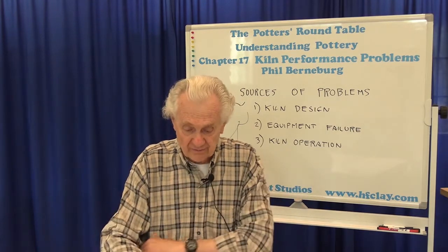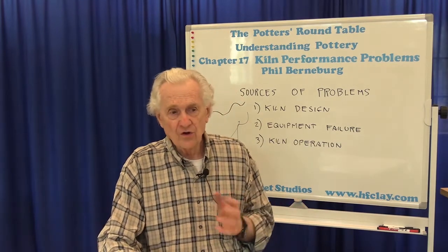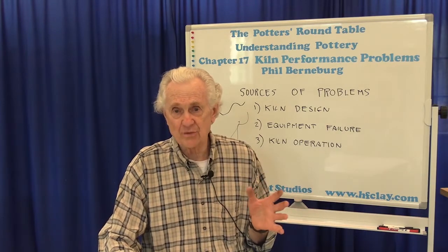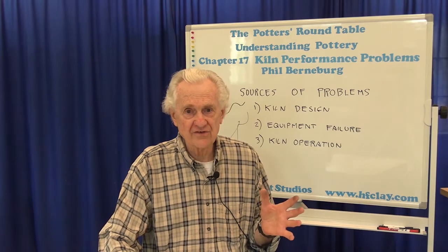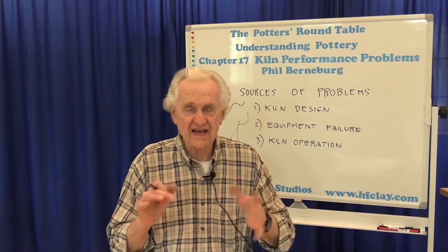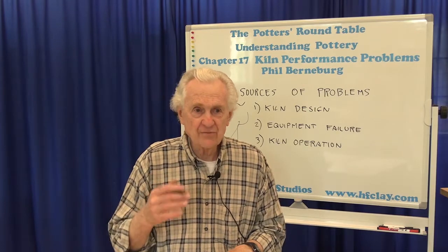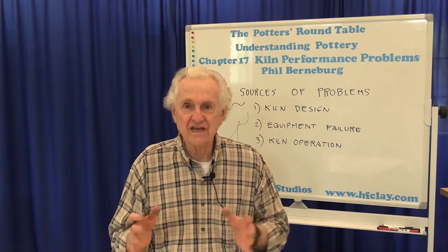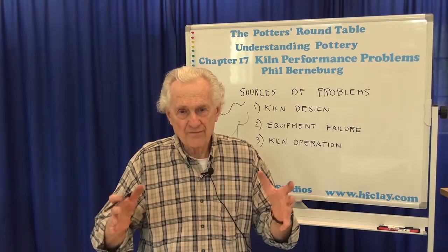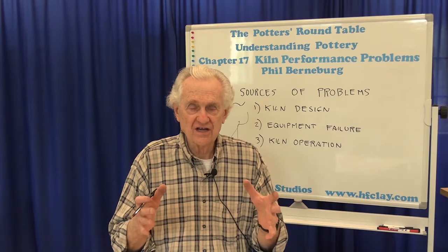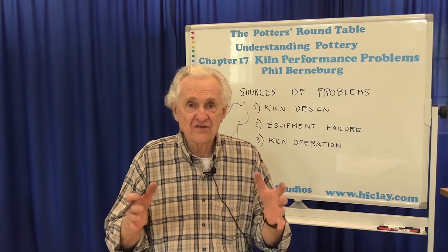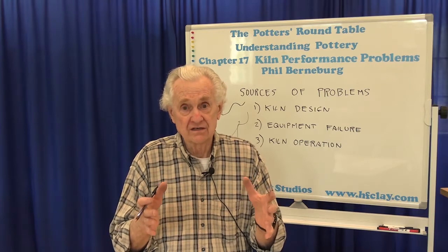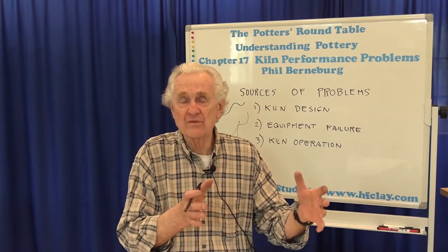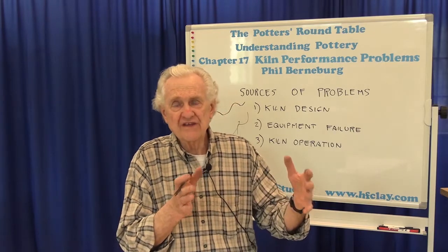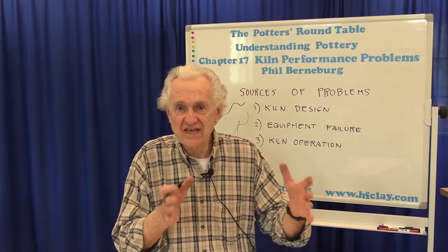But there also could be equipment problems. One of the things that's different about most wood kilns compared to gas kilns or electric is that almost all of them are made with hard or dense fire brick, which you need to have in order to resist the corrosive effects and the slag and the ash that's going to accumulate. But hard fire brick is a terrible insulator, and it absorbs a lot of heat. So with a wood kiln, you've got a lot more mass of the kiln that has to get hot before the pots and everything else inside can get hot. So there's just a lot more that has to be heated than with most gas kilns. Most gas kilns, or a lot of them at least, are built with either refractory blanket or insulating fire brick, which doesn't take as much heat to heat up the kiln.